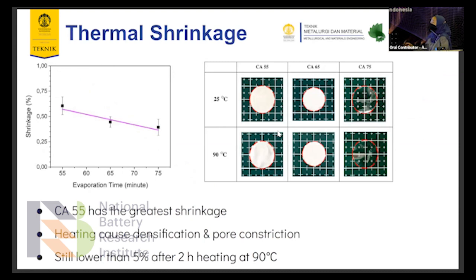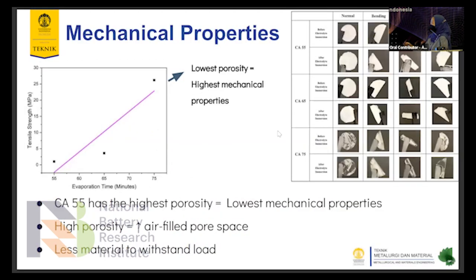The thermal shrinkage is also related to the porosity. The 55-minute membrane has the greatest shrinkage. This is because heating will cause densification and pore constriction. So that membrane will have the greatest shrinkage. And then the mechanical properties, the porosity is also related because the membrane with the highest porosity will have more air-filled pore space, so there will be less material to withstand the load, so it will have the lowest mechanical properties. In this term is the tensile strength. We also observe the bending, and then the rolling, and then the folding to observe its mechanical properties using a physical method.